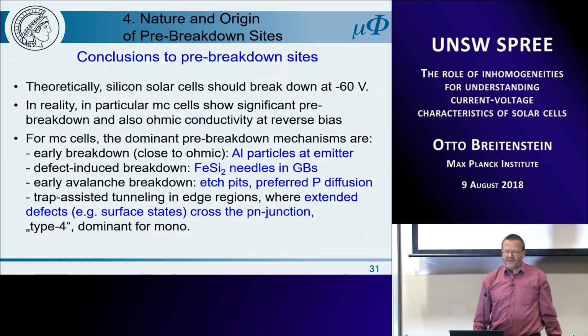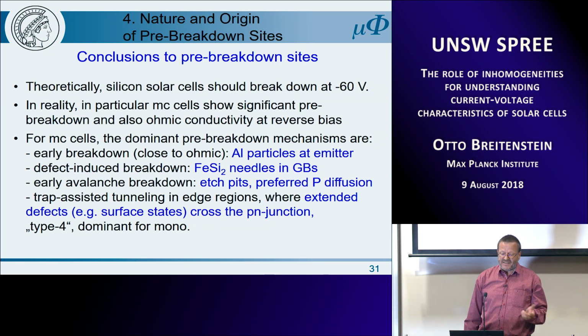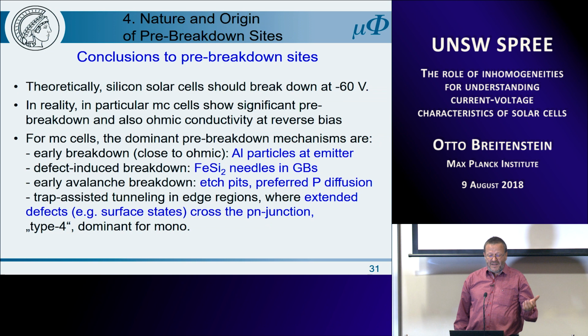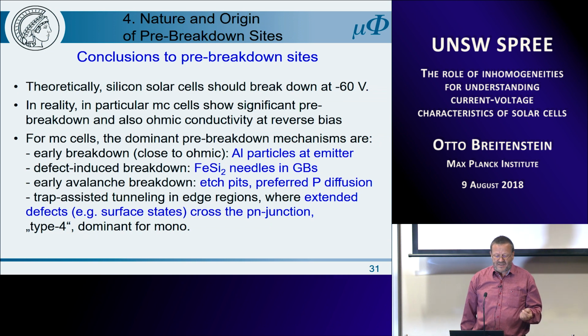So the conclusions to pre-breakdown sites are the following. Theoretically, silicon solar cells should break down at minus 60 volt. In reality, it happens much earlier. And so the dominant pre-breakdown mechanisms are early breakdown close to ohmic, aluminum particles at the emitter, defect-induced breakdown, iron silicide needles in the grain boundaries, early avalanche breakdown at pits or edge pits or preferred phosphorus diffusion defects. And last but not least, trap-assisted tunneling in edge regions where extended defects, for example surface scratches, are crossing the pn-junction, and I propose to call this type 4 mechanism. And this should be dominant for monocrystalline cells.